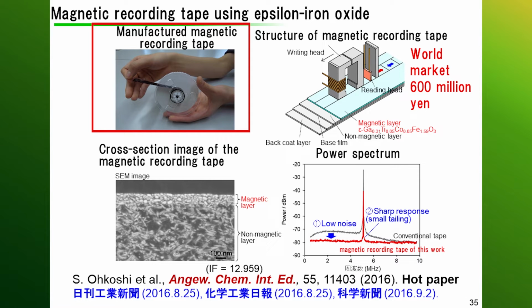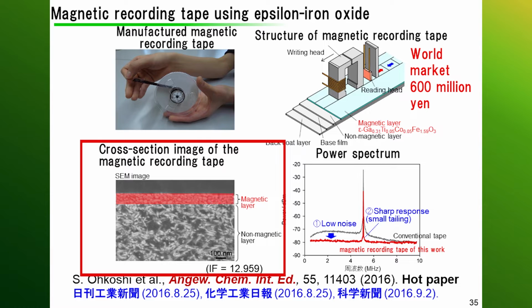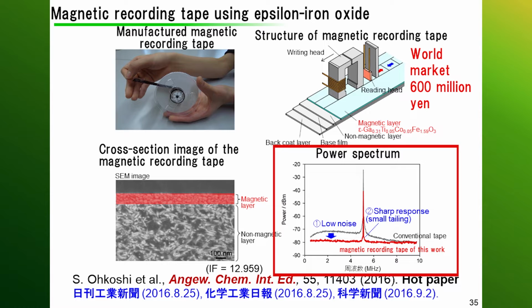The photo shows the manufactured magnetic recording tape using powder we developed. You may not have seen these magnetic tapes, but they are very important. The other photo shows the magnetic layer of the tape. The size is below 100 nanometers. The power spectrum shows a very sharp increase, demonstrating that the replay signal is very effective as a magnetic tape.